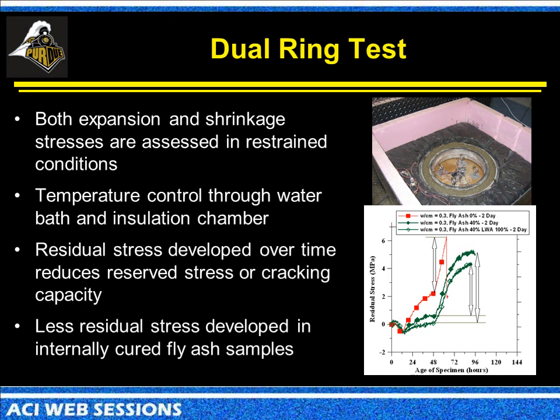The ones where we had the fly ash and we had the fly ash with internal curing, we actually changed the temperature 30 degrees Celsius. We dropped the temperature 30 degrees Celsius and didn't see cracking in either the fly ash system or the internally cured system because you have less built-in residual stress in the overall system. And we can see that this goes out.